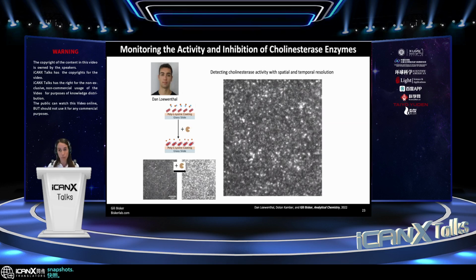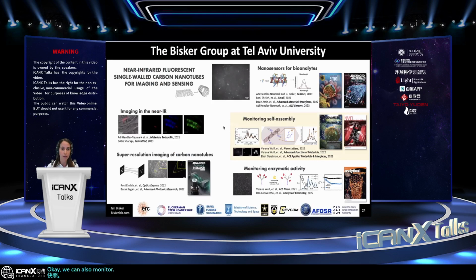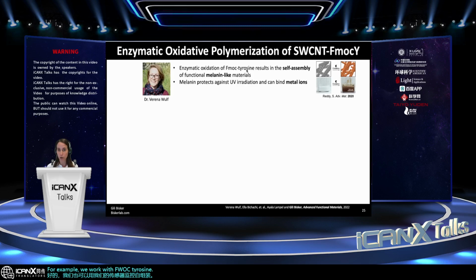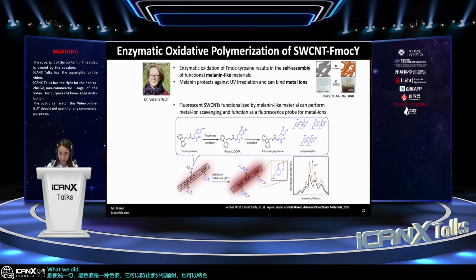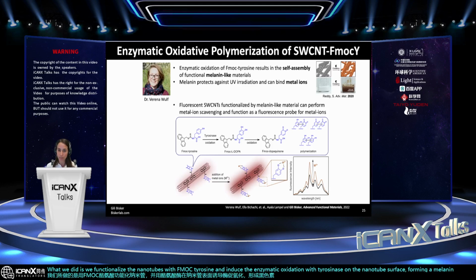We can also monitor self-assembly with our sensors. For example, we work with FMOC tyrosine. The enzymatic oxidation of FMOC tyrosine results in the self-assembly of functionalized melanin-like material. Melanin, by the way, is a pigment, and it protects against UV radiation, and it can also bind metal ions. What we did is we functionalized the nanotubes with FMOC tyrosine and induced the enzymatic oxidation with tyrosinase on the nanotube surface, forming a melanin-like coating of the nanotubes. And then upon the interaction with metals, we can also get fluorescent response to the metal binding.